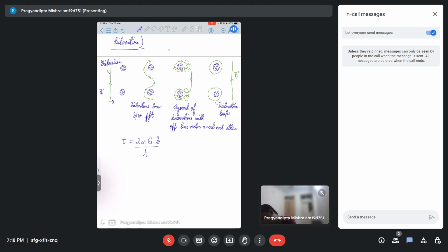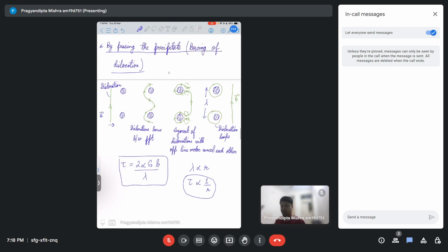So, lambda is essentially the distance between the two precipitates. Lambda you can say is proportional to kind of like r. So I can say tau is proportional to 1 by r. This is a corollary that you can take from this. Okay. This relation you can remember for bowing of dislocation.